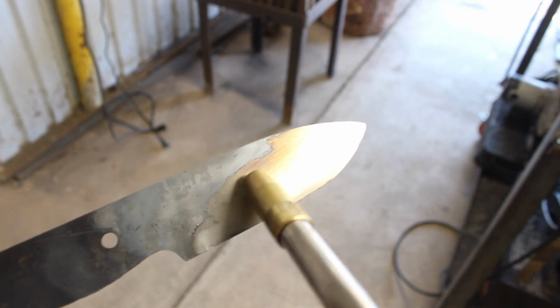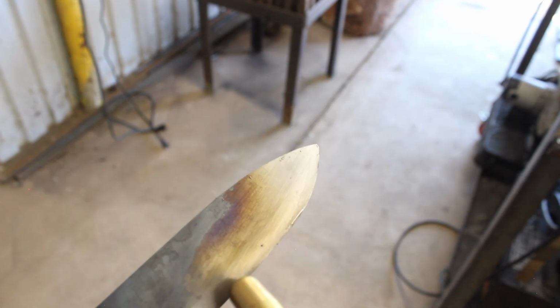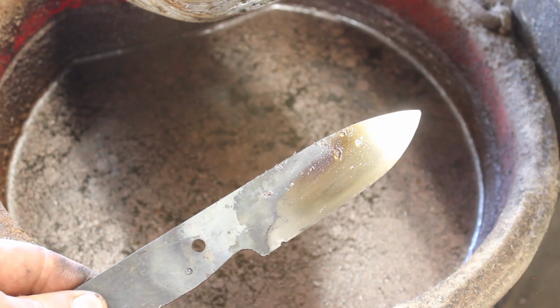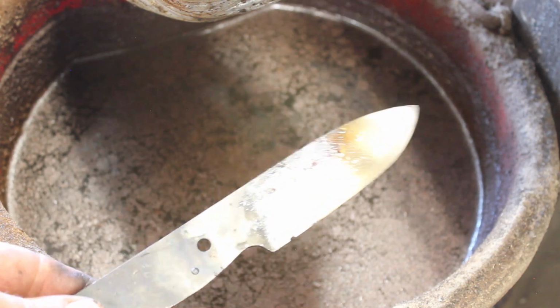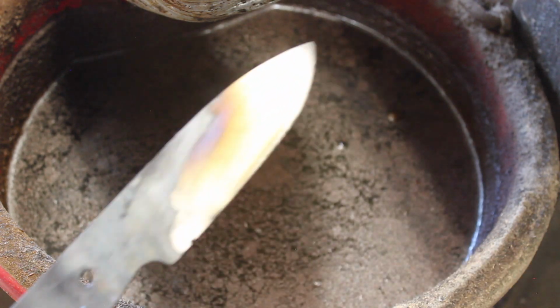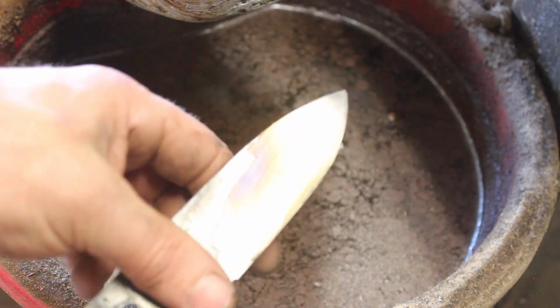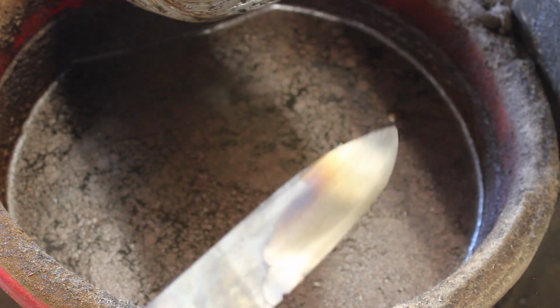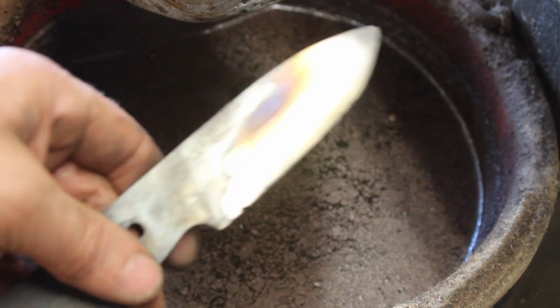So you see I already have a dark straw here. I've got to go dip that in water. Typically I do this right by a water pan, and I should have mentioned that a minute ago. I just cooled this off because that right there is the color that I want. You really don't want to do it like I just did, where I had to move across the room to stop the heat on this, because that can easily be far too long, and you can temper your blade out too much, lose too much of the hardness.